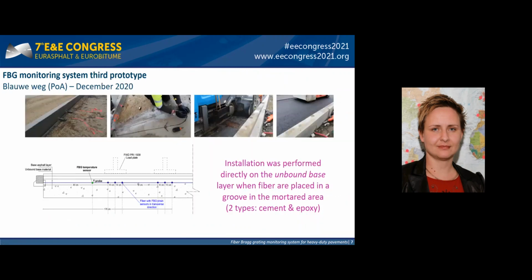Considering the difficulty of installation of FBG sensors in prefabs, an alternative solution was tested in Test Blauweg in the Port of Antwerp last year in December. The installation was performed directly on the unbound base layer, where FBGs were placed in a groove in the mortared area, and two mortars were tested, cement-based and epoxy-based. The survival rate showed 100% of sensors survived, and a temperature sensor was also placed next to the area. This installation was mostly meant for performing falling weight measurements.